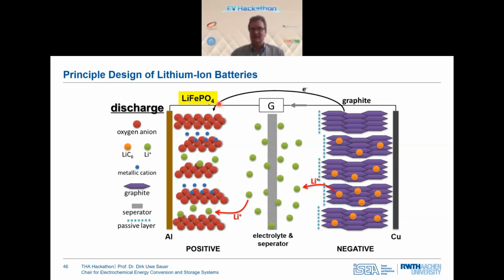Nevertheless, LFP is interesting because it is more safe than the nickel, manganese, cobalt oxides, and it could generally be cheaper because iron and phosphate compared with cobalt or nickel are really cheap. But the disadvantage of lithium iron phosphate is that the energy density is 25% to 30% lower compared to best NMC battery technologies in class today. So LFP, more safe, maybe cheaper, but definitely at lower energy density.